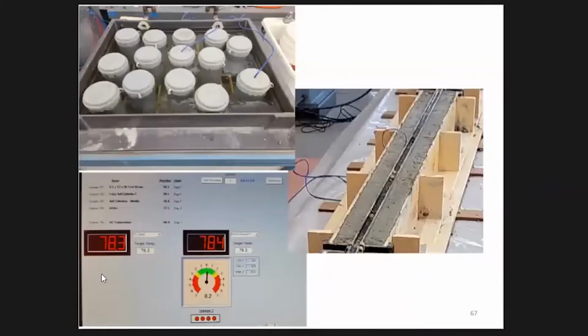To make sure we had exactly the right release strength, we put a thermocouple in the prism, which is bigger volume than the little 4x8 cylinder that we're going to use for strength. I then developed the software and system. We drive a water bath so that the temperature of the cylinders is exactly slave to the temperature of the beam, and they're usually within a half a degree.